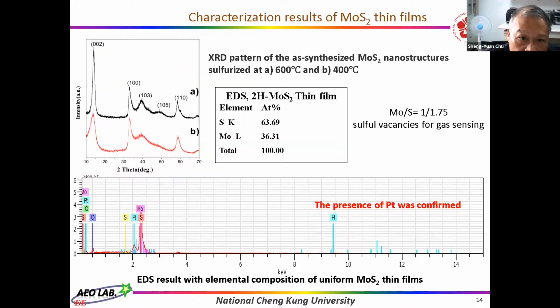This figure shows the X-ray pattern of the synthesized MoS2 nanostructures with two different stabilization temperatures. The black one is 600 degrees, and the red one is 400 degrees. And we cannot see any big difference in these X-ray patterns.